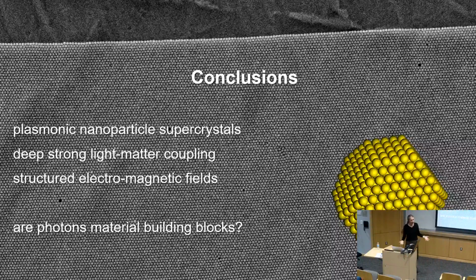The point is that the nanoparticles are really huge compared to quantum dots or other particles that have been used to produce superlattices. Because they are so large, the variation in the length of the polymers is not so important anymore. So only steric repulsion is used. Yes, absolutely. Nothing else. I mean, we have now started to talk about using charged brushes for these gold nanoparticles, because that would help in producing non-FCC structures. So, for example, to promote the sodium chloride structure or cesium chloride structure, if we had positively and negatively charged particles, that would, of course, be very beneficial. But we haven't started with that.